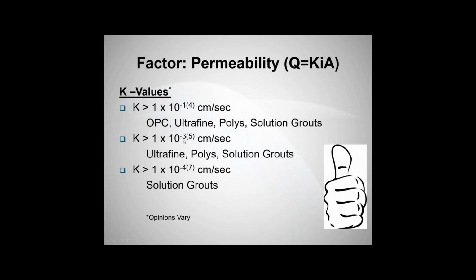As that material starts to tighten, gets less permeable, from a range of 3 to 5, now you're probably looking at an ultrafine cement, a poly, or a solution grout. And then as it gets even less permeable, that range tightening to 4 to 7, now you're probably looking at a solution grout like chemically reactive grouts.